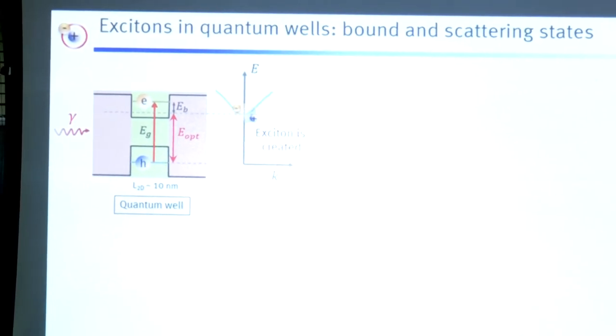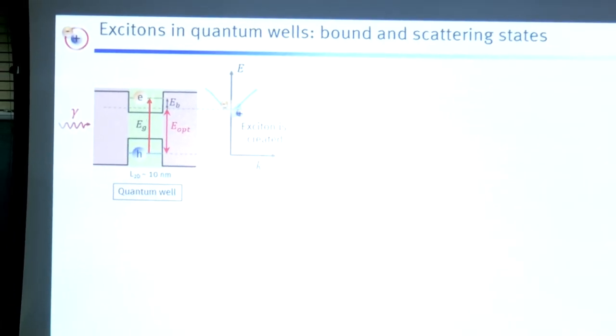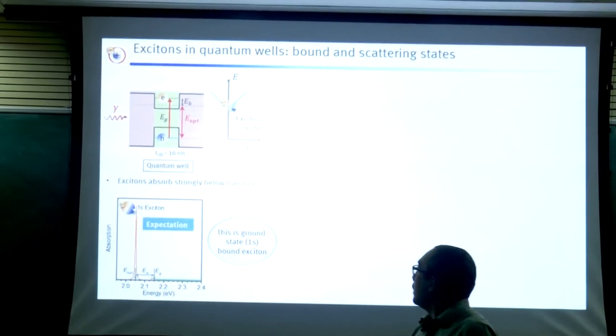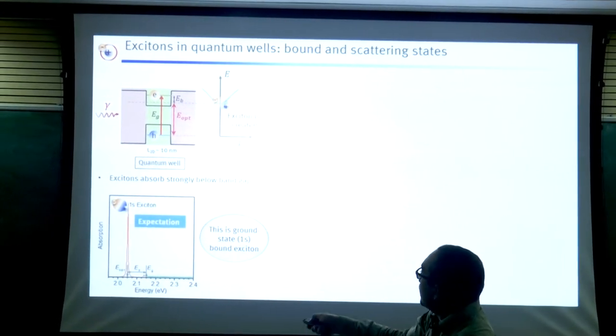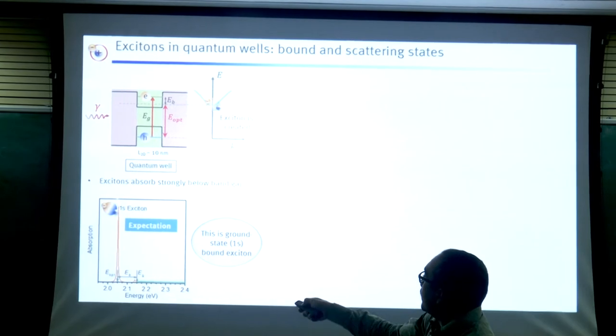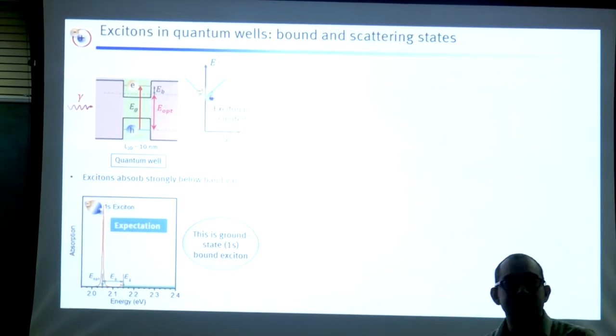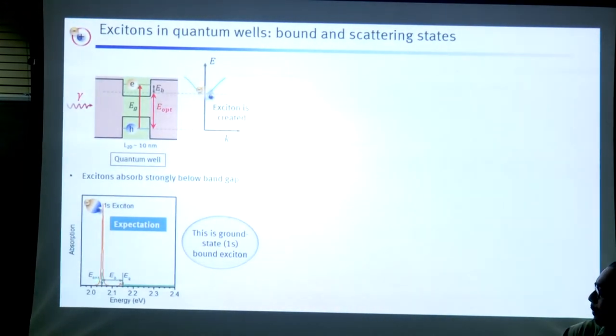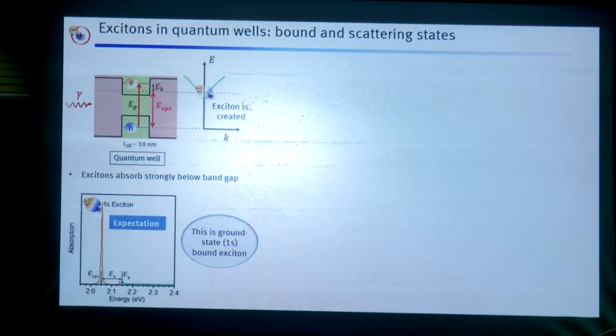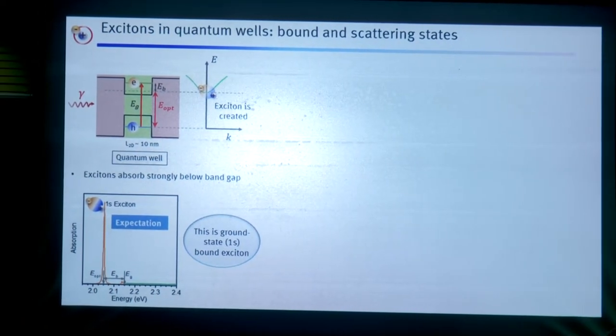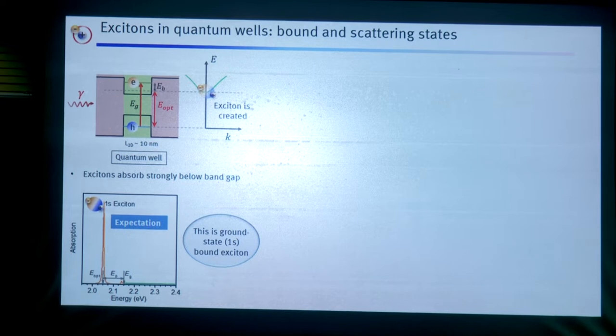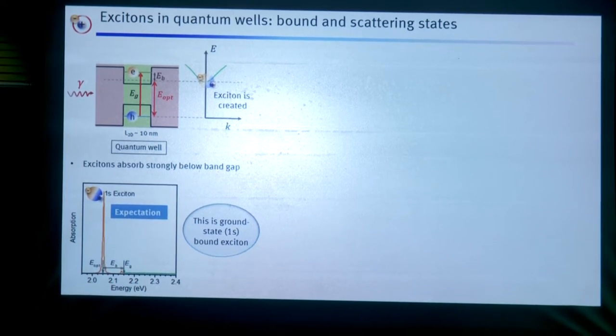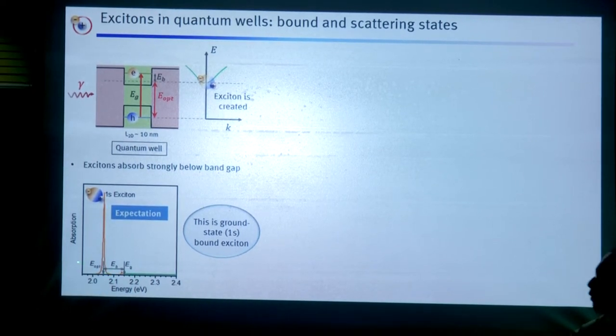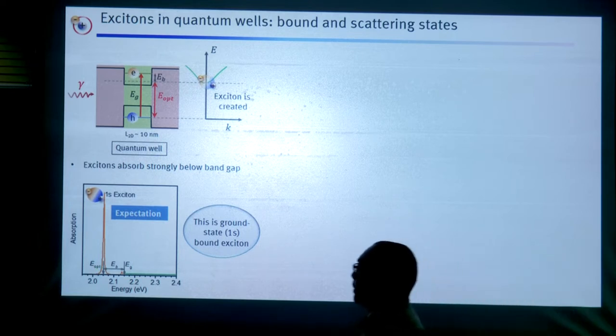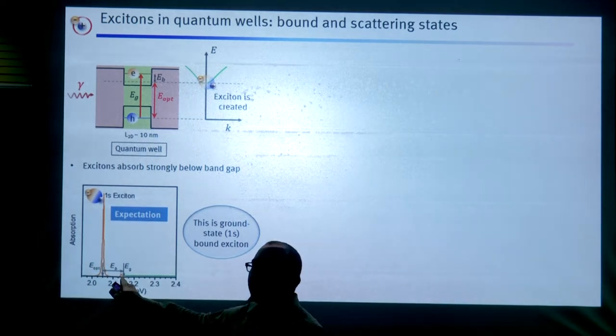Let's suppose you have a transition. An electron-hole pair is created, an exciton is created in such a quantum well. Okay. Theoretically, you expect that this exciton should appear as a very strong resonance just below the band gap. Now, why below the band gap? Because an exciton is a bound state and binding reduces the energy. So this is created below the band gap by an amount equal to the binding energy. So this is the place where the transition happens, but this is the place of the band gap.